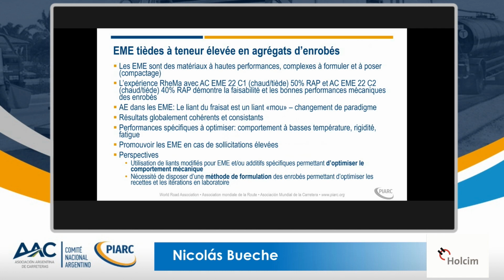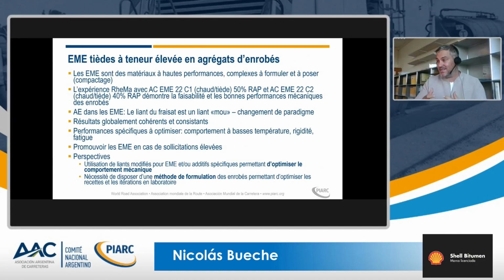As I told you, the aspect of RAP in high modulus asphalt is a bit tricky because the binder from the RAP is a soft component and not the hard component in that case. From a general point of view, for the lab test, we get rather coherent and consistent tests, and we could also see, this is already known, that pen and ring and ball are not always sufficient. We need some more testing, more precise tests.